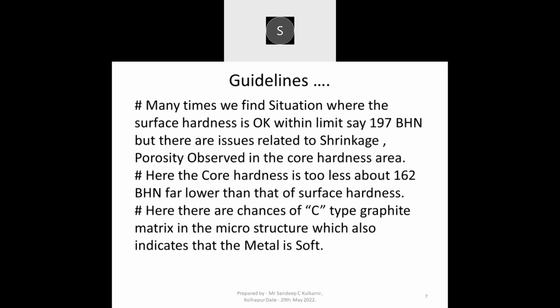Many times we find situations where the surface hardness is okay within limits, say 197 BHN, but there are other issues like shrinkage, porosity, or microporosity observed in the core hardness area. Here the core hardness is too less, about 162. So your surface hardness is 197 BHN, and there are issues like shrinkage or porosity or open grain structure. When you cut the casting and check the core hardness of that same casting, it is around 162. So there is a gap of almost 35 BHN between the core hardness and the surface hardness.